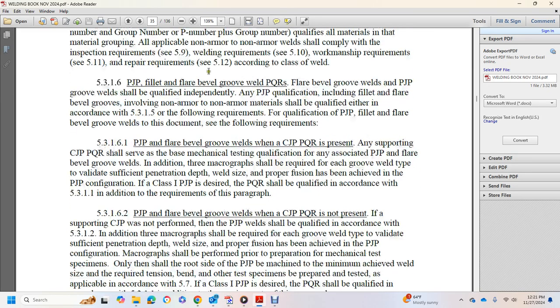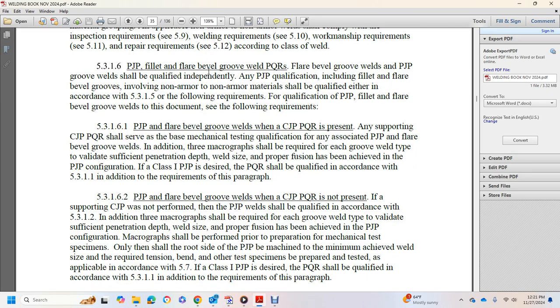to the requirements of the paragraph PJP for the flare bevel groove weld. Where the CJP performance qualification record is not present to support the CJP, and not performing the PJP weld qualified in accordance with 5312, in addition 3 macrographs are required with each groove weld to validate sufficient penetration and depth of the weld side with proper fusion to achieve the PJP configuration. Macrographs should be performed prior to the preparation of the mechanical test specimen, which only show the root side of the PJP to be